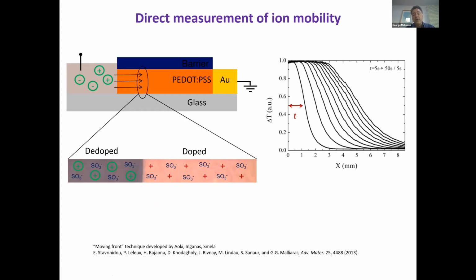Now, continuing a bit further with evidence of ideal behavior, if you wish, we did this moving front experiment following along the steps of others such as Aoki, Smela, and Inganas, who did this type of measurements. Here we did them in one dimension. So we made a geometry where we have a PEDOT film, we have a barrier on top, a barrier on the bottom, and we can only inject ions from the side.